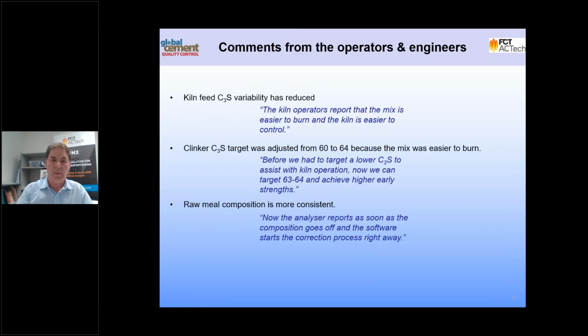So we talked to the plant operators and tried to get some idea what they thought about all of this, and they were very much happier, basically because they found the mix was easier to burn and the kiln was much easier to control. One of the important factors for them was that they were able to adjust their C3S target up from 60 to 64, because before they had to target that lower C3S value simply to get better kiln operation, and now they're able to target 63 to 64 and achieve much higher early strengths.